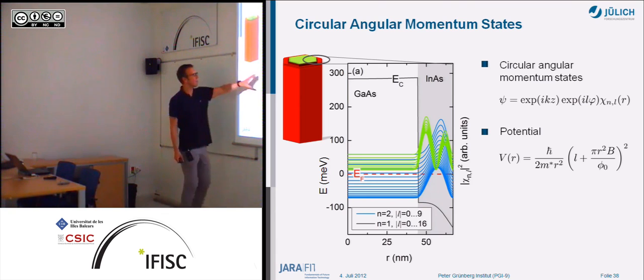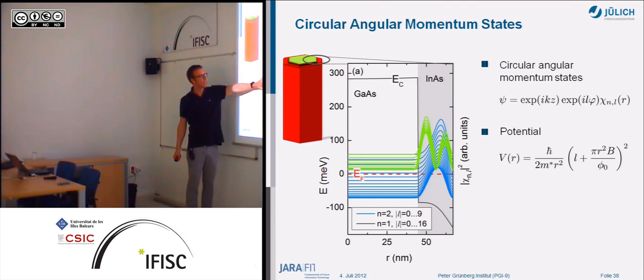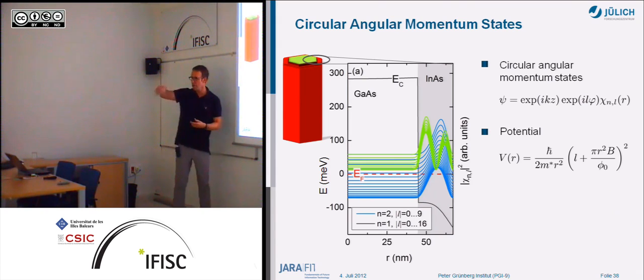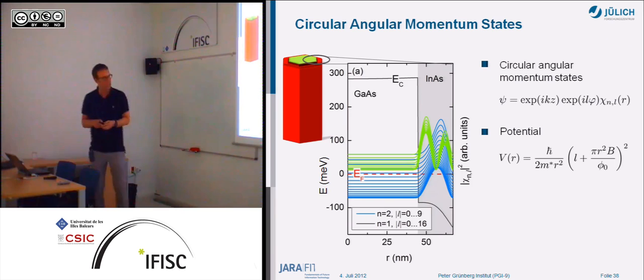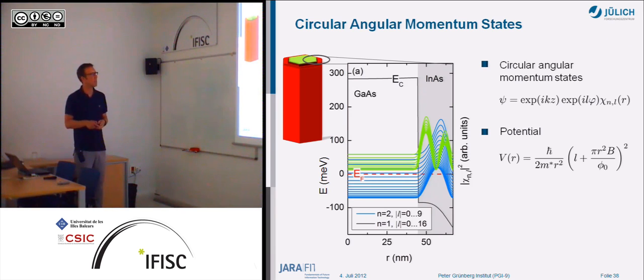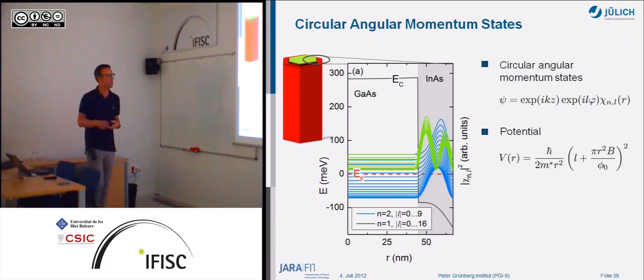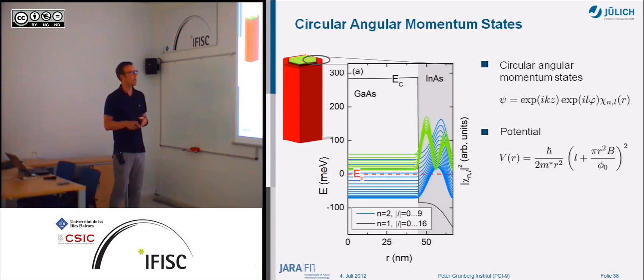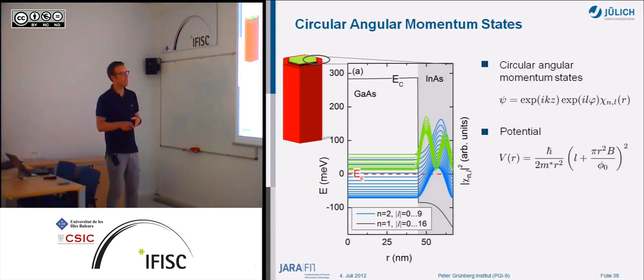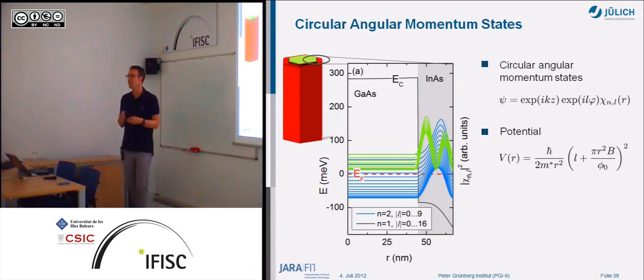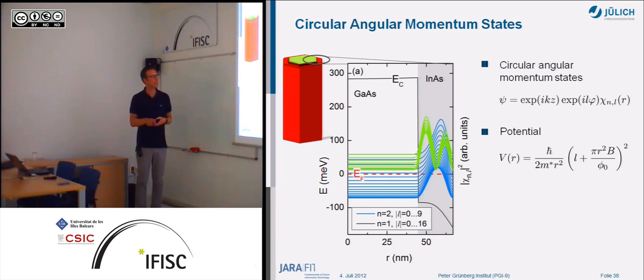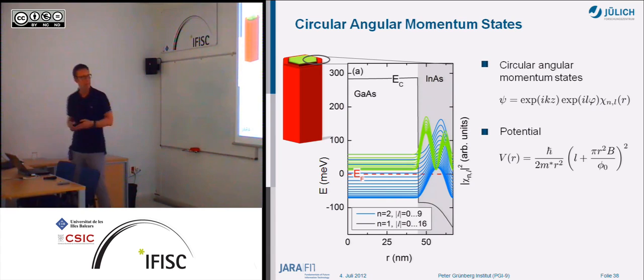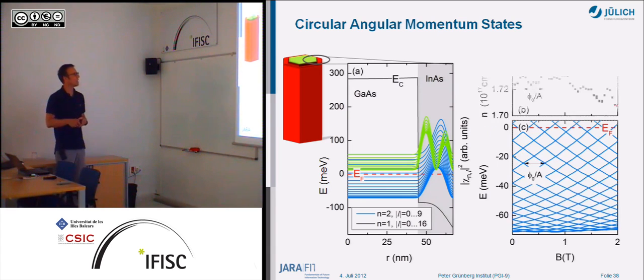What determines the energy spectrum here is, on the one hand side, because we have the circular motion of electrons, the angular momentum. It's the angular momentum state here. And if you apply a magnetic field, you also have to include the vector potential, which ends up in this term here, which mainly puts in the magnetic flux normalized to the flux quantum. That's what determines the potential. And we would like to look at the magnetic properties.